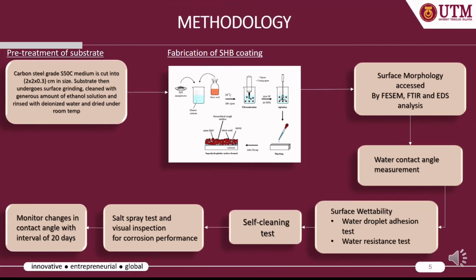As for the characterization, the surface morphology of the coating samples was assessed by FESEM, FTIR, and EDS analysis, water contact angle measurement, surface wettability, which are water droplet adhesion and water repellency tests, self-cleaning test, salt test, and visual inspection for corrosion performance evaluation, and lastly, monitoring the changes of contact angle with an interval of 20 days.